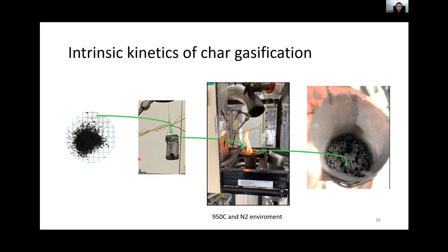The fast char of the microalgae is prepared with this fluidized bed reactor. I put the algal particles in a wire basket and immersed it rapidly into the reactor. So the particle can be heated quickly and it devolatilizes quickly. And after devolatilization, you can see the flames because the volatile is burned close to the exit of the reactor because we have some oxygen on the top. But the reactor was still in a nitrogen environment at 950 degrees. And after quick cooling down, we got a fast char. I crushed and saved the char and used it in kinetics experiments.